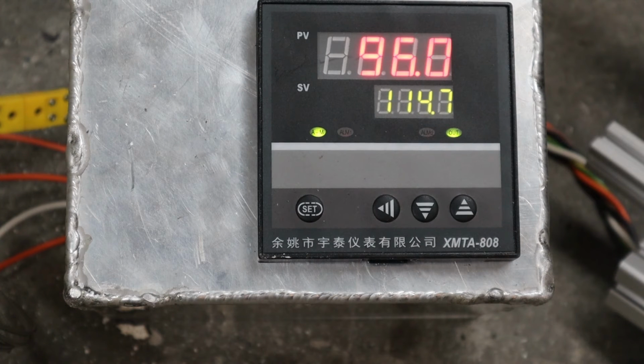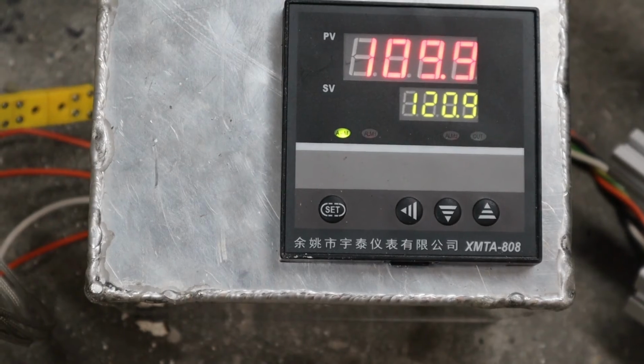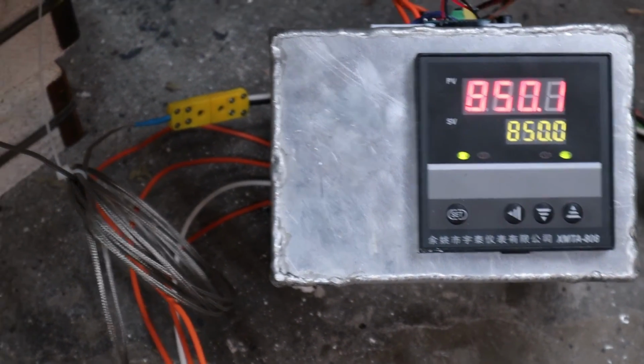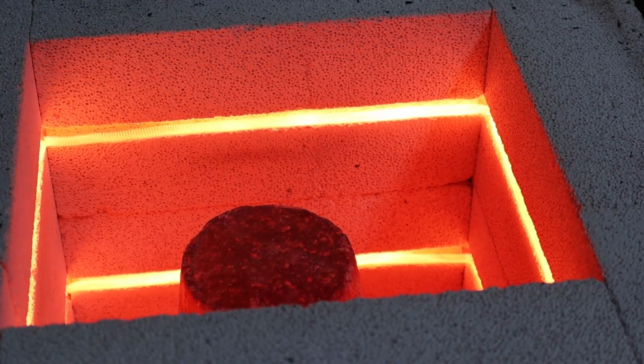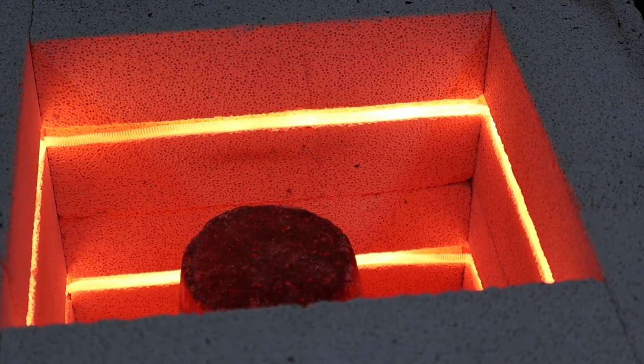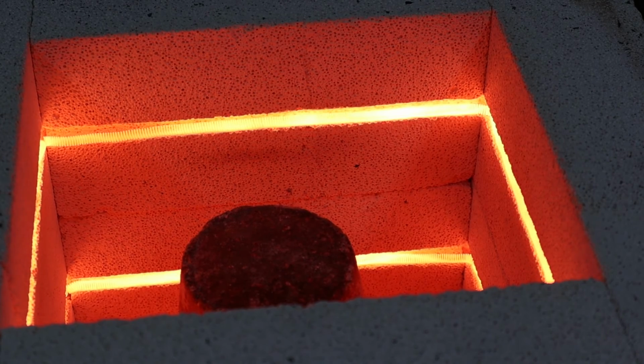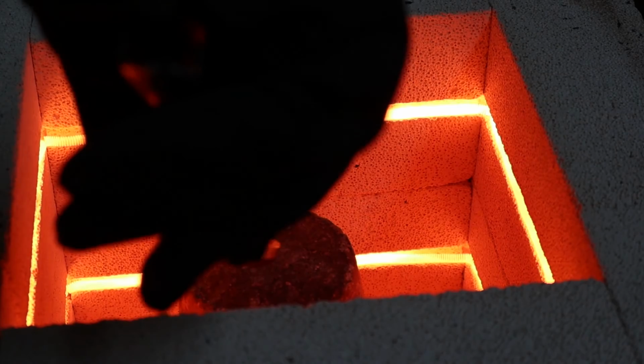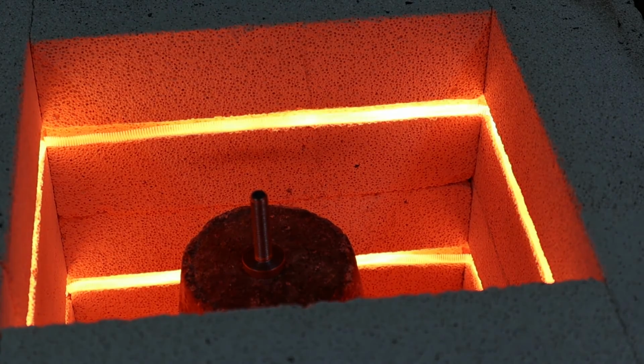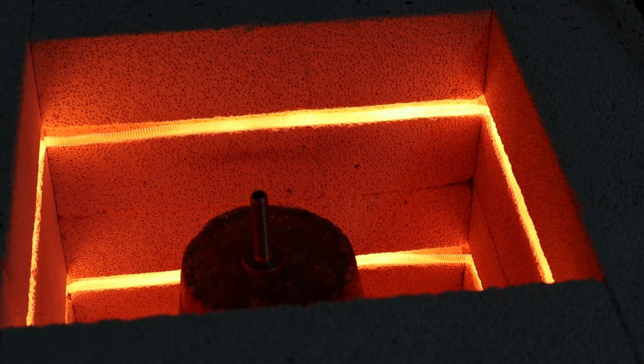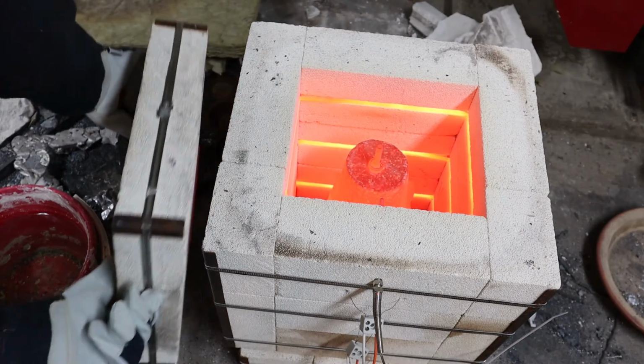Okay, hardening of the screw for hardness. This means heating up to 850 degrees and soaking there for half an hour, and quench in water.